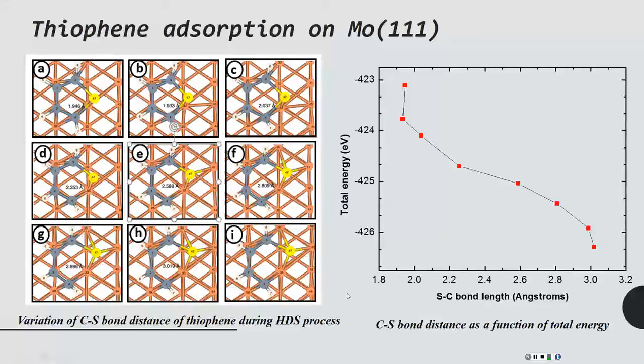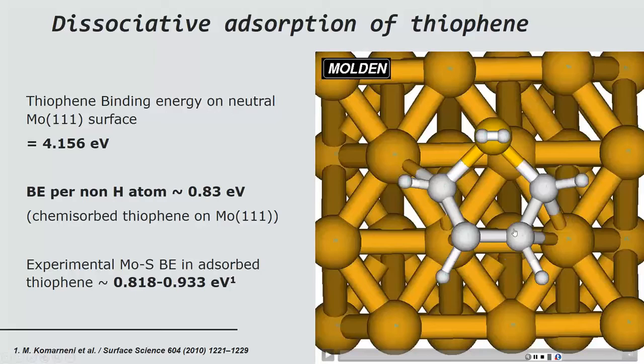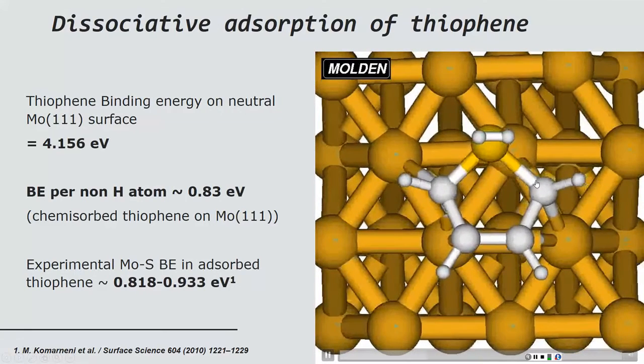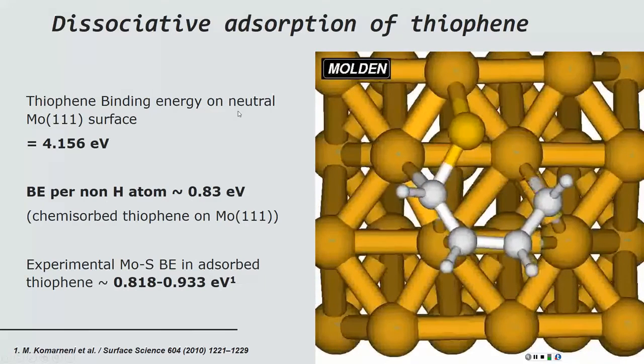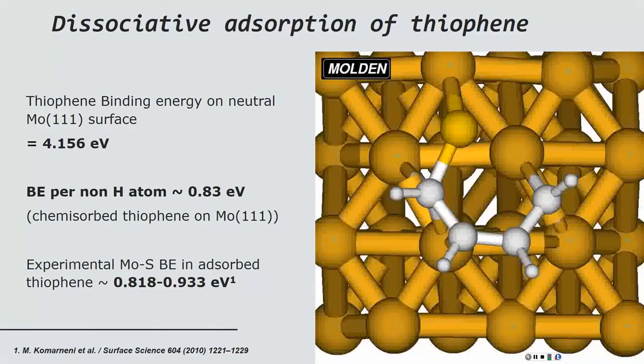Here you can see the variation of carbon sulfur bond distance during this adsorption process. As you can see, with time one of these carbon sulfur bonds is dissociating. This bond is elongating and dissociating. Here you can see the carbon sulfur bond distance as a function of total energy. As the carbon sulfur bond distance increases, the total energy of the system decreases. That means the system tends to stabilize by dissociating this carbon sulfur bond. This movie further illustrates the dissociation of this carbon sulfur bond during the adsorption process. So this further confirms that thiophene is dissociatively adsorbing on these catalytic surfaces.